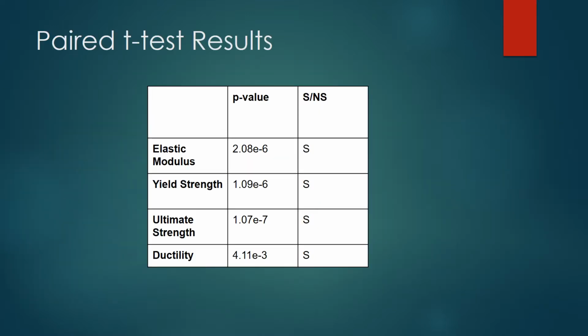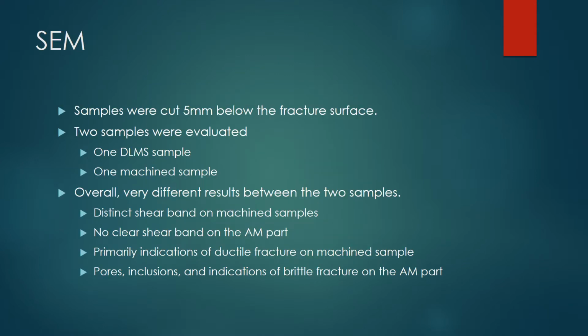We conducted paired t-tests comparing these four mechanical properties that you see here between the machined samples and the printed samples. They returned these p-values, which are all below the type 1 error rate that we set of 0.05. As such, all of the results are significant, meaning that there is indeed a difference between the two types of samples. And now I'll pass it off to Gabe.